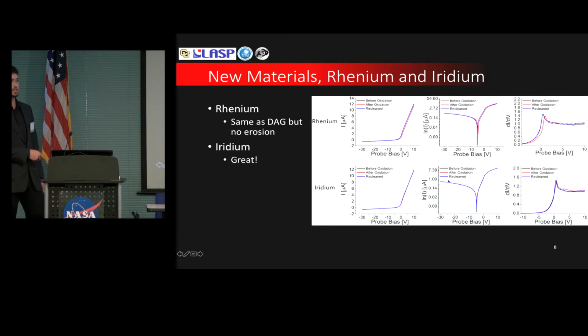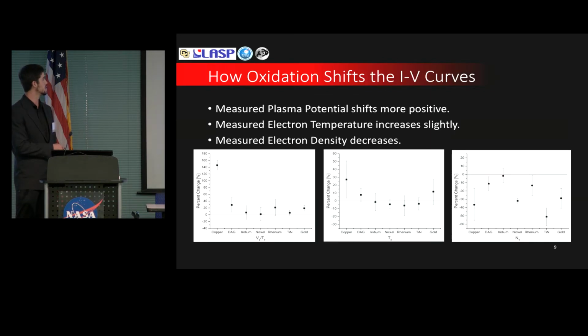The curves stacked up one on top of each other, almost perfectly. So, this definitely seems to suggest that for a new probe coating, for a Langmuir probe that is intended to be used in the upper atmospheres of planets, magnetospheres, etc., anywhere where there's going to be a lot of atomic oxygen, Iridium definitely shows promise as being a candidate for these probes.